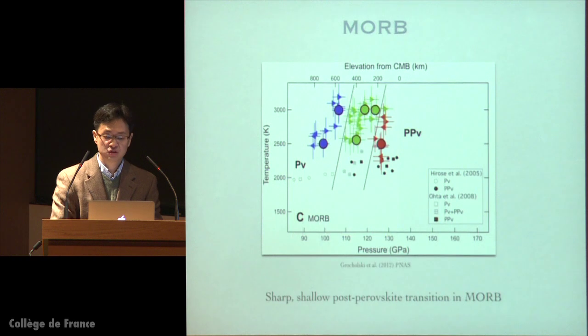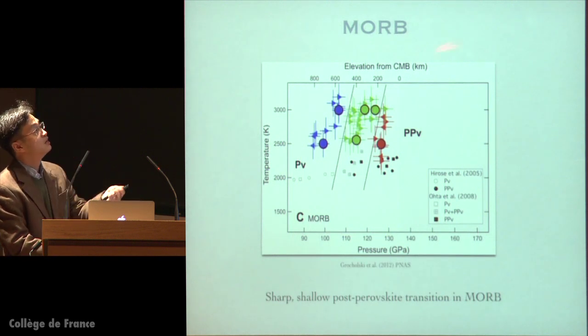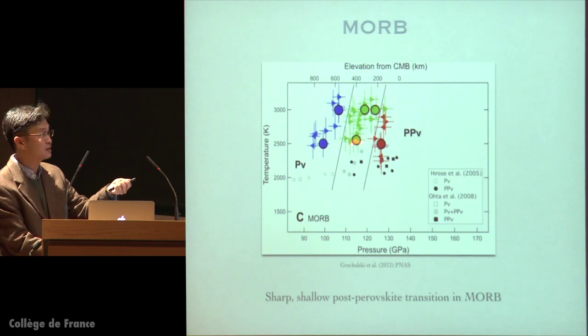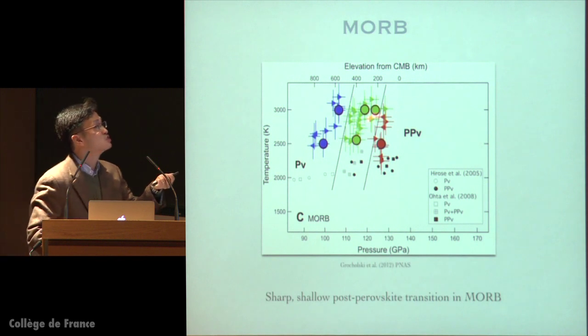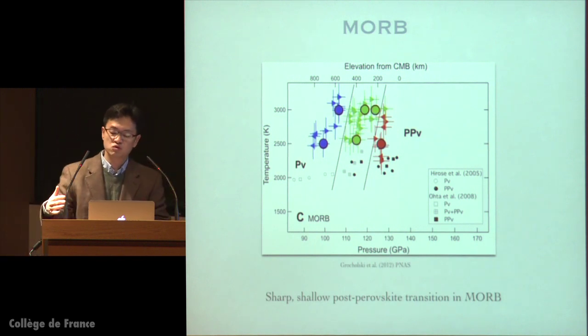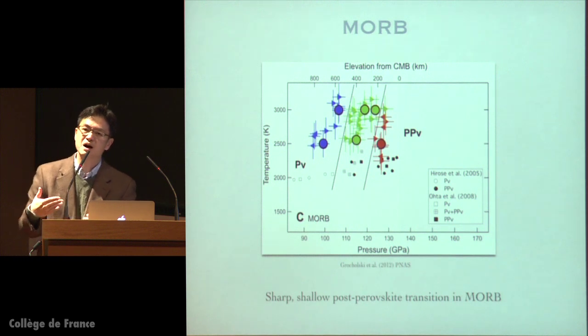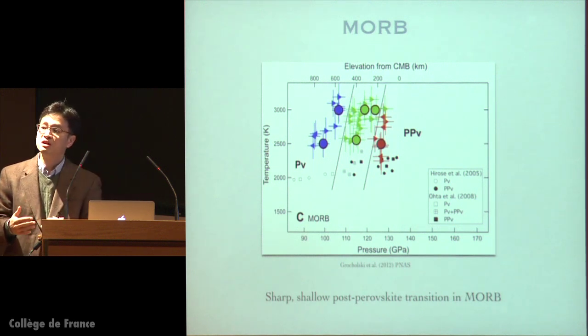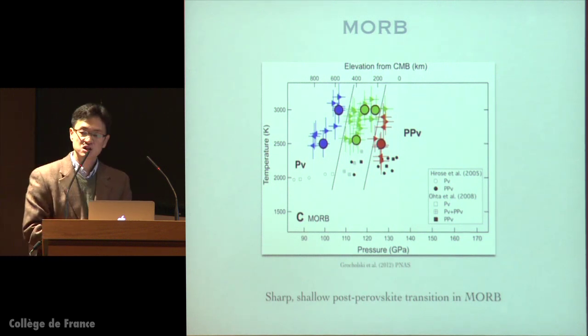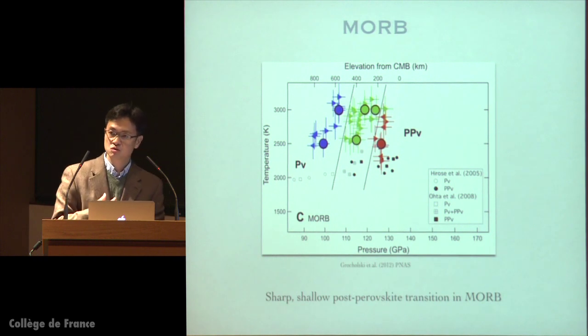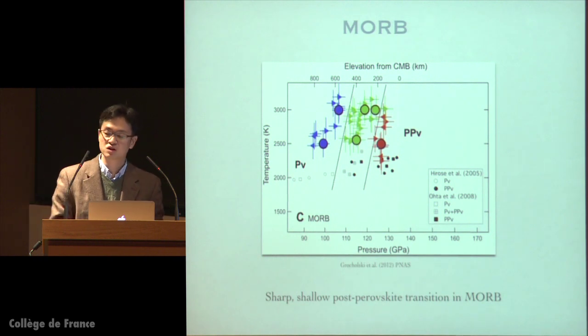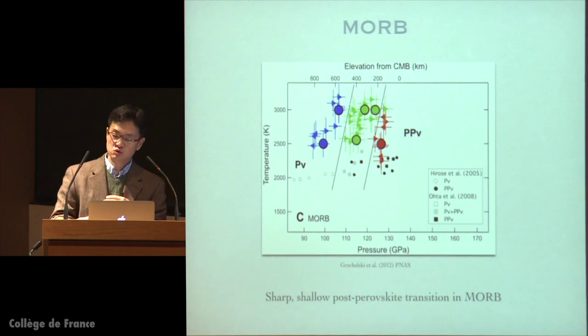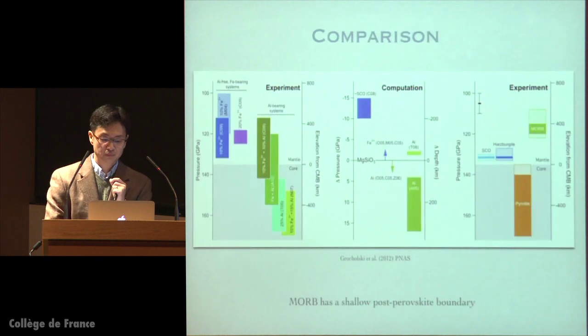But in fact, we saw a little funny thing going on. Again, this is our core-mantle boundary. There seems to be a shallowing effect rather than a deepening effect. And we do see some thickness here, up to about 300. If you take the lower bound, it's about 100 kilometers. But it's definitely smaller than the thickness we observe in pyrolitic composition, which ranges about 400 to 500 kilometers, which seems counterintuitive given the fact that morb has more aluminum.